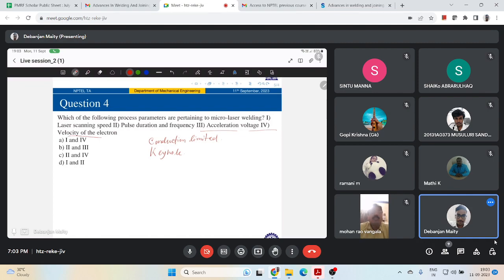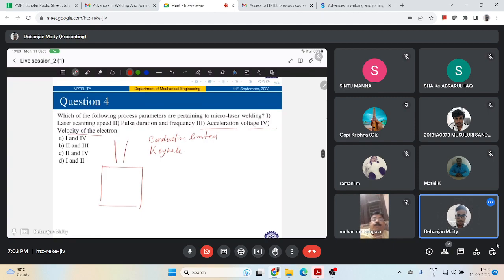Keyhole and conduction limit. In conduction mode, if this is my laser beam, the penetration depth is somewhat less than in keyhole mode. So you are thinking of this keyhole as penetrating into the surface and making the depth very deep. In conduction mode, the power density is less than in keyhole mode, and you are heating the workpiece above the melting temperature without vaporizing, right? And here the penetration is controlled by conduction.